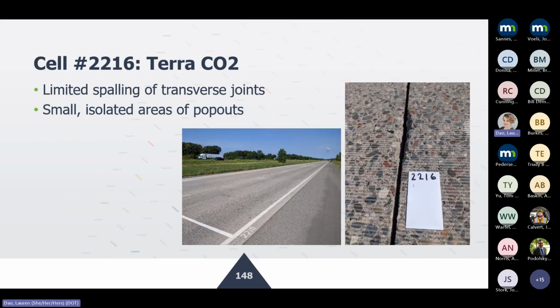And 2216 Terra CO2, same thing, transverse joints. In a lot of the transverse joints, we see some low severity transverse faults. And then there were some isolated areas of pop-outs. Other than that, no cracking, no shrinkage issues, seems to be doing pretty well after year 1.